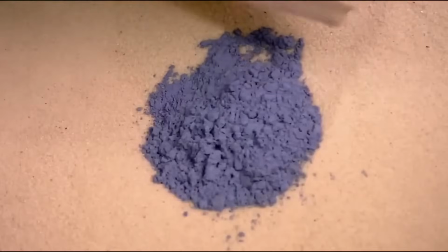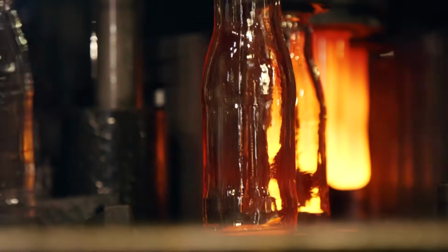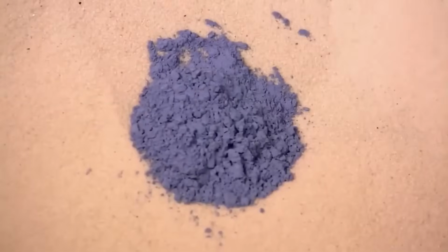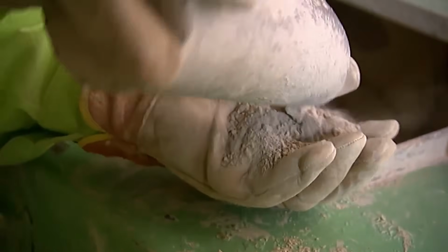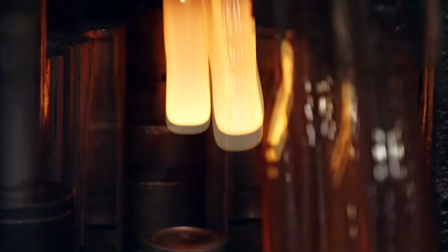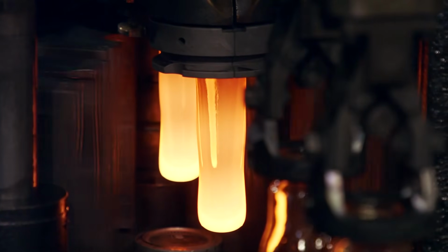One additional ingredient enters the mixer: cullet. This is recycled broken glass from previous production runs, reintroduced at rates between 20 and 30% of total batch weight. Cullet melts at a lower temperature than virgin raw materials, reducing furnace energy consumption by approximately 3% for every 10% of cullet added. A factory running at 30% cullet content saves enough energy annually to power several thousand average households.